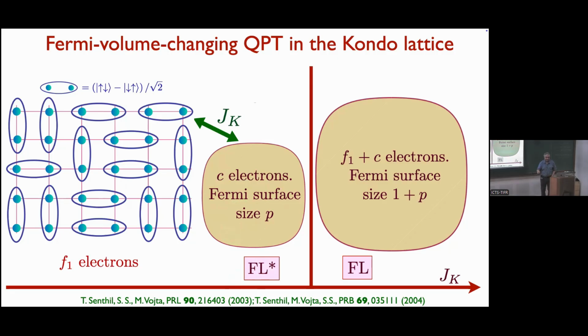But the more familiar state, which is present in essentially every heavy fermion material, is the Fermi liquid, where you get a large Fermi surface, where the Kondo effect runs off to infinity. And that means you get some hybrid quasi-particle, which combines both the f and the c. And then the Fermi surface obeys the Luttinger theorem. The size of the Fermi surface is 1 plus p, 1 for the spins and p for the electrons. This is the state I'm interested in. And in this state, effectively, the spins have bound to the electrons and become a large Fermi surface.